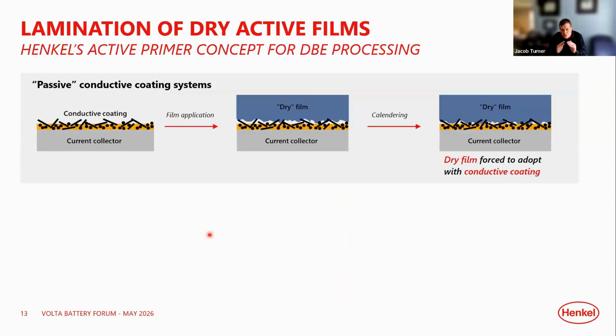So again, let's walk through the importance of the material selection and understanding of a process from a conductive coating standpoint. Here I'm going to introduce you to two terms, a passive and active conductive coating system. This passive conductive coating system is what we just talked about. More of a rigid, true coating, no real lamination behavior, just an enhanced surface roughness. When we try to put the dry film on that, we can use all kinds of heat and pressure and we force the dry film to adapt to that conductive coating. What ends up happening is you get point adhesive contacts. You don't get this nice blended interface.